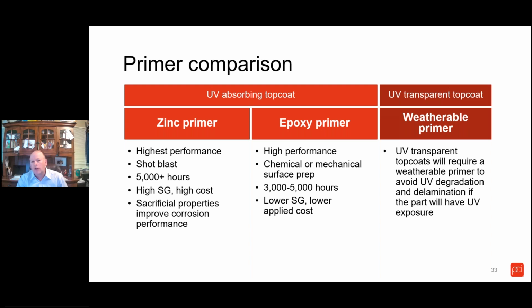The other thing I want to note: if your part is going to be exposed to UV, if it's going to be outside where it's exposed to UV rays, you want to make sure that if you're using an epoxy primer, your top coat is UV absorbent. Your powder supplier can tell you if it is not a UV absorbing top coat.